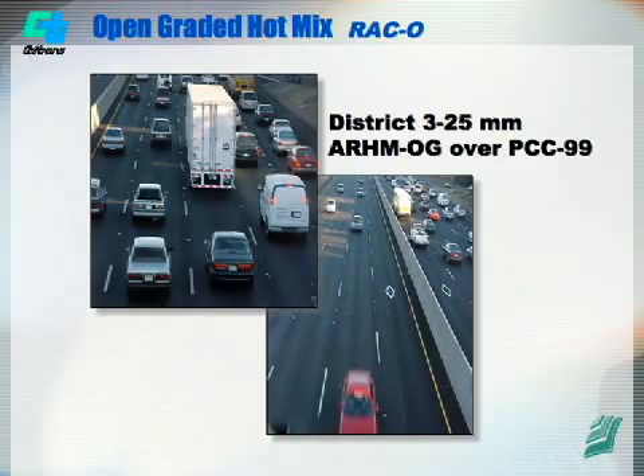Of course, in addition to the other benefits of helping against oxidation of the surface, with the anti-splash and reducing hydroplaning. Open-graded hot mix has been used on the freeways here. This is one of the experiments or the pilot projects that we've done with the pilot program, where we put this in one of our districts on I-80, that's the freeway that goes from San Francisco to Reno, and has been performing well. And of course, Arizona has been using a strategy like this for several years.